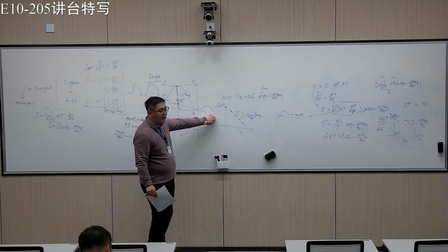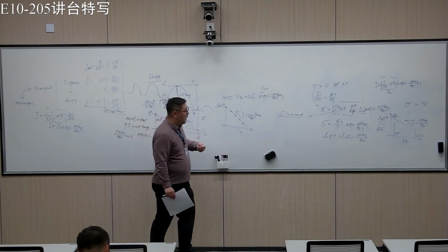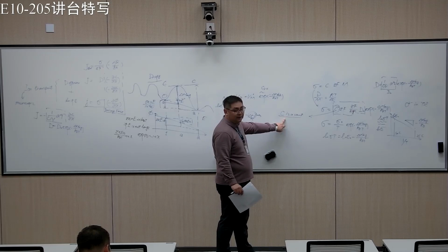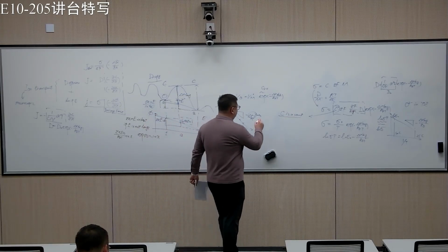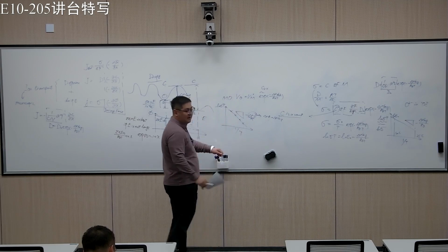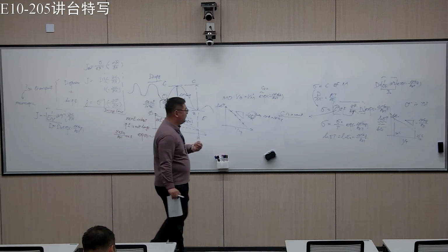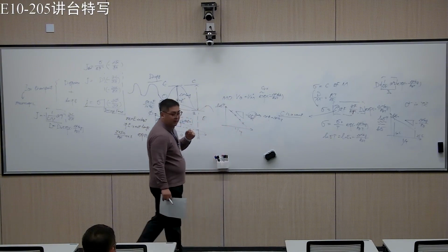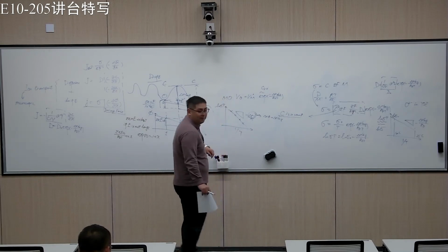However, for halide perovskite or for other material systems, you cannot really assume that the defect concentration is a constant. Now you have the formation energy times the migration barrier. So they are convoluted. You have to fix one of these to get the two things out. Otherwise you may have these two things together.